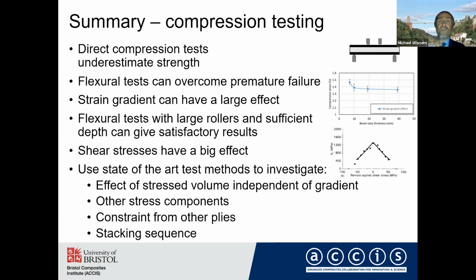The shear stresses have a big effect, but there's other components that are not so clear. And what I think we should do now is to use these state-of-the-art test methods, such as this bending I've just shown with the sandwich specimen, to really look at some of these things in more detail. What is the effect of the stress volume independent of the gradient? What about the effect of other stress components? What about constraint from other plies and stacking sequence effects? So far, we haven't really been able to look at these because of difficulties with the test methods.